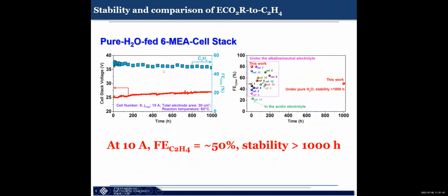So overall, the stability for our stacked 6 MEA cells can be more than 1,000 hours. And for the C2H4, they maintain a pretty high level, close to 50%. Because of the stacked cell, we also improved the Faraday efficiency from about 43 to about 50%. And the voltage we use is about 25, and as time goes by, we increase it a little bit. So this is a very encouraging result.